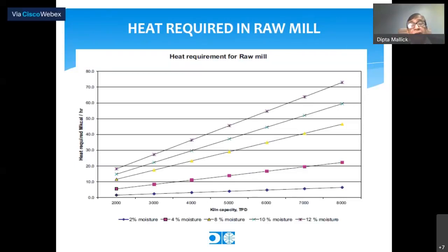This chart gives the entire thing in a nutshell: what is the heat requirement in raw meal, and we have given various charts corresponding to 2% moisture, 4% moisture, 8% moisture. You can see that at, say, 6,000 ton per day capacity, if you have around 4% of moisture, then you need about 15 megacalorie per hour of heat, which is actually required for useful purpose in the raw meal. So this we have to tap, and in spite of tapping this amount of energy, you are still left with a sufficient amount of energy. We are coming to that.